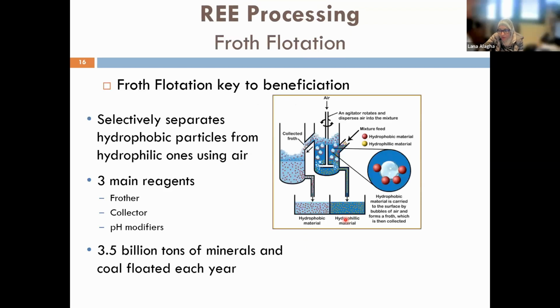Froth flotation is key to beneficiation in rare earth. Froth flotation is a three-phase separation process. It is more complex, so the design of a flotation circuit or plant is more complicated compared to other physical beneficiation like gravity or magnetic separation, but it is highly selective. Ideally, in the lab, you can float anything from anything, by understanding the nature of your material and by modifying the surface chemistry of its different components. But the challenge is how to upscale the process.